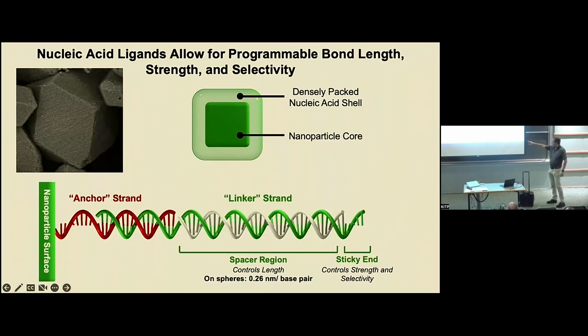But you'll see we have anchor strands, we have linker strands. The length allows you to control bond length. Every base you add, 2.6 angstroms of distance in terms of bond length. We've mapped that out beautifully. It's a very linear relationship. And then we have a recognition element at the end, which is a lot shorter than most people would design if you wanted to create duplexes, because you have cooperative interactions, many of these coming together at the interface between two particles that cooperatively bind and lead to a stronger interaction.